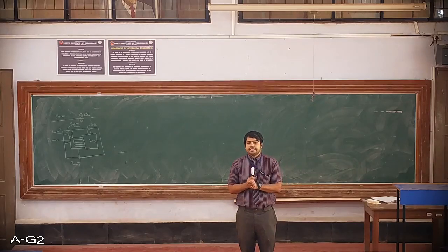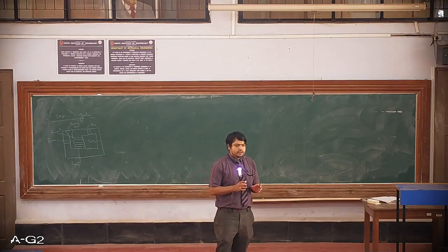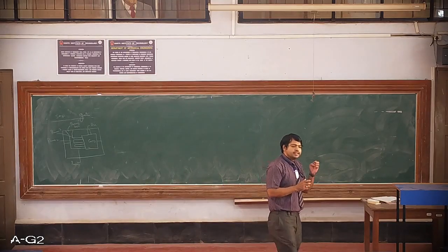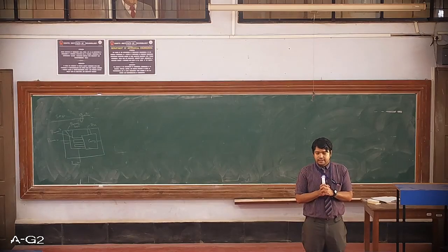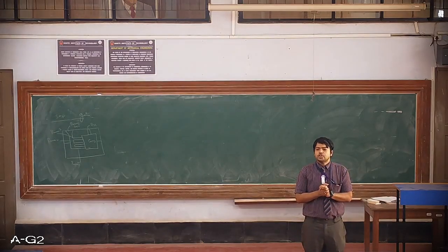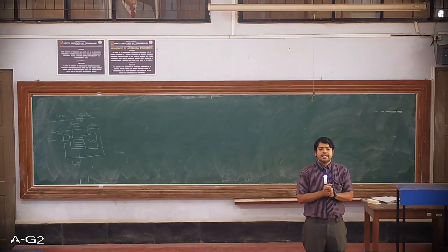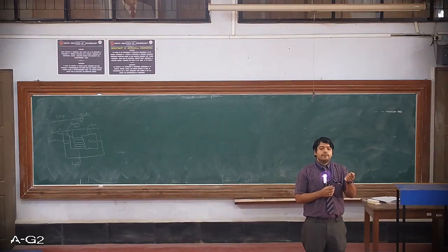Another important aspect is the type of binders we are going to make use of. That plays a very important role. Because in case of green sand molds, the gas evolution will be very less, whereas in case of chemical bonded molding systems like no-bake molds, the gas evolution is predominant. Always keep in mind, the gas evolution should not exceed 14 ml per gram. Suppose 1 gram of sand if you take and heat it, it should not generate more than 14 milliliters of gas. That is what this gas evolution indicates.